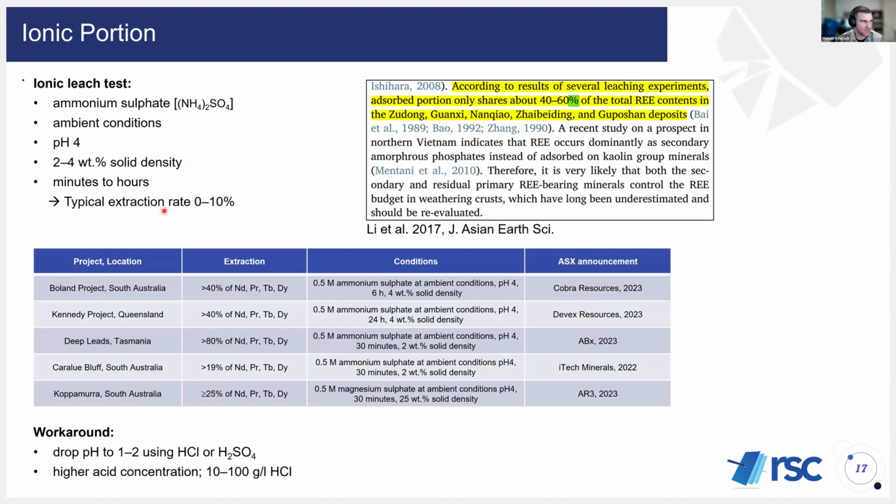But on the downside, the typical extraction rate that companies are getting is just 0 to 10%. So not overall, not that high. And that's what's been published on ASX. On the ASX overall, our leach tests are still pending for the MREEVA project, so I can't even make a comment on that. But that's overall the number we see quite regularly, 0 to 10%.